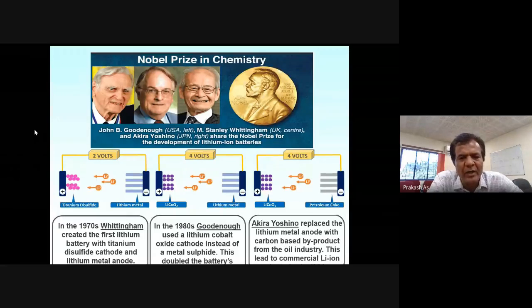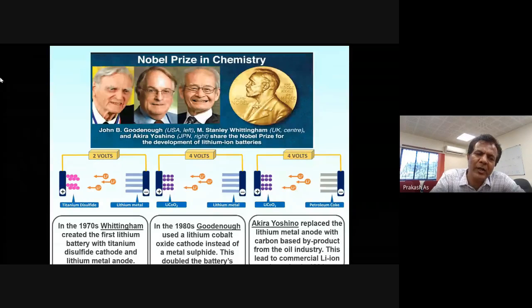And then after about 10 years, Professor Goodenough came up with another novel material. Instead of titanium disulfide, he invented a new material, lithium cobalt oxide. This is also a layered compound, with a layer structure like titanium disulfide. One advantage here is that the oxidation state of cobalt in lithium cobalt oxide is 3+. When you remove lithium, it goes to 4+. So the redox of cobalt from 3+ to 4+ happens around 4 volt. Just by changing the chemistry of the material, he showed 4 volt. So from the initial 2 volt demonstration, we increased the voltage up to 4 volt.